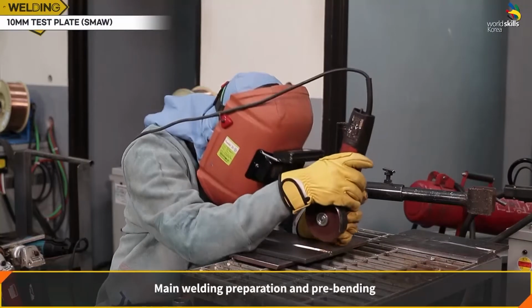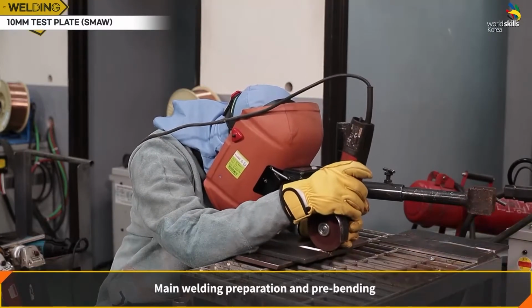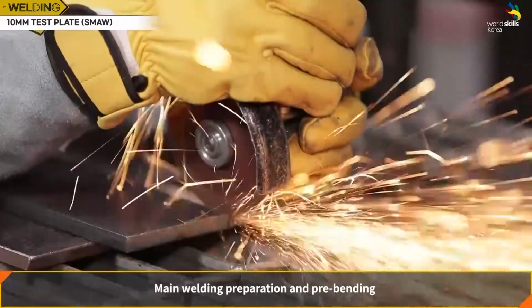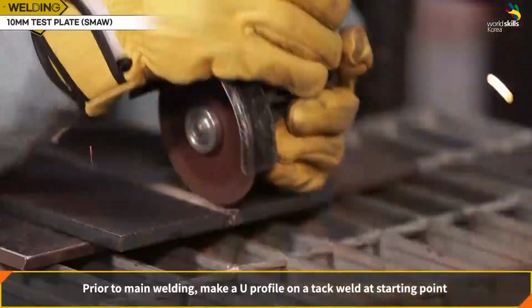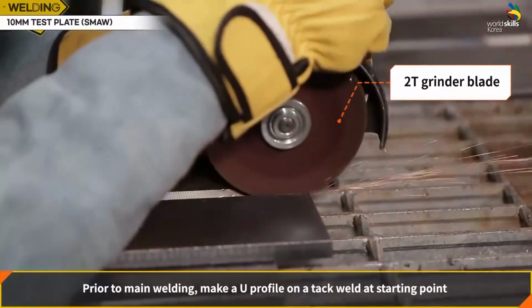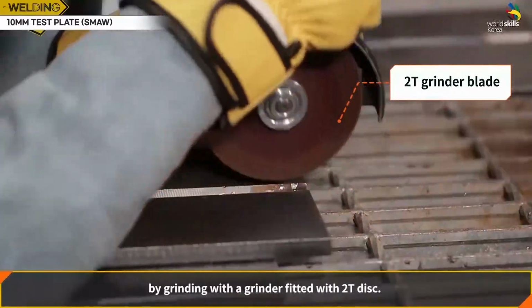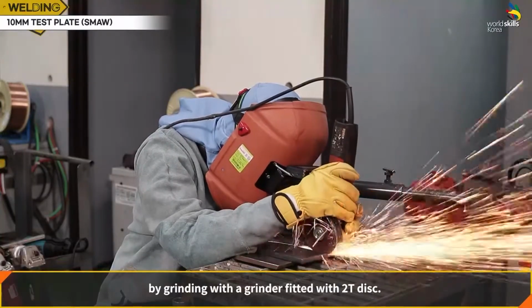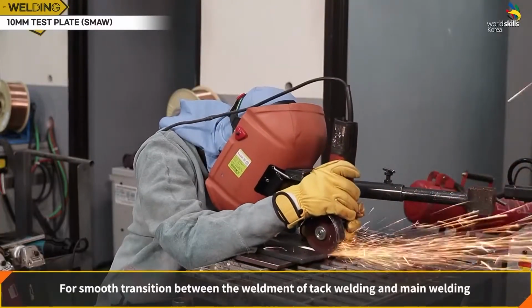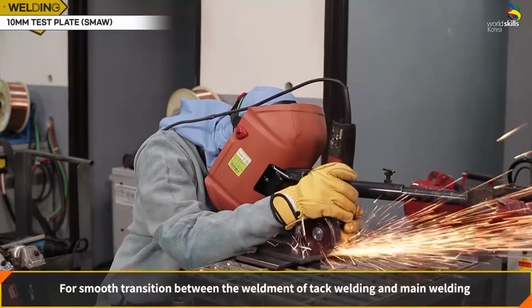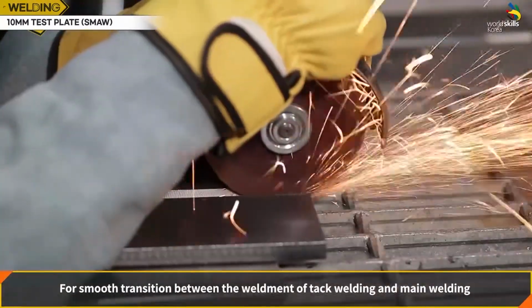Main welding preparation and pre-bending. Prior to main welding, make a U-profile on a tack weld at the starting point by grinding with a grinder fitted with a 2T disc. The reason for shaping with a grinder is for a smooth transition between the weldment of tack welding and main welding.